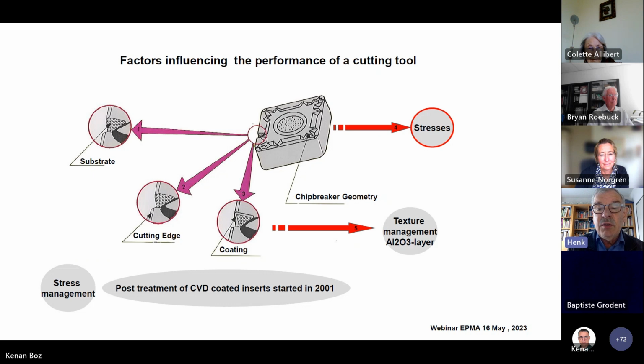Later on, in the beginning of the 2000s, 2001, stress management was introduced in CVD. It was known from PVD that you have compressive stress, and we had always tensile stress in coatings, and we found out how to change that by blasting processes, by post-coat treatments. And very important, especially pushed by the company Sandvik, was what I call the texture management of the aluminum oxide layers, which again gives very good improvements in machining performance. These five components are very important to make a very good cutting tool.